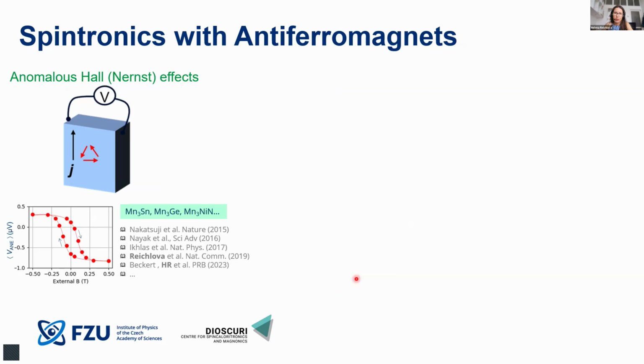So probably one of the simplest and well known already since Lord Kelvin, and all these times when they had a piece of ferromagnetic material, is the anomalous Hall effect, which refers to a transversal voltage detected perpendicular to the current and some magnetic order parameter. This anomalous Hall effect was historically considered to be proportional to the net magnetization, to be present only in the ferromagnetic metals. However, there was a very inspiring history happening, and already when I did my PhD, there started to be some hints that the anomalous Hall effect has components which do not need to rely on the net magnetic moment.